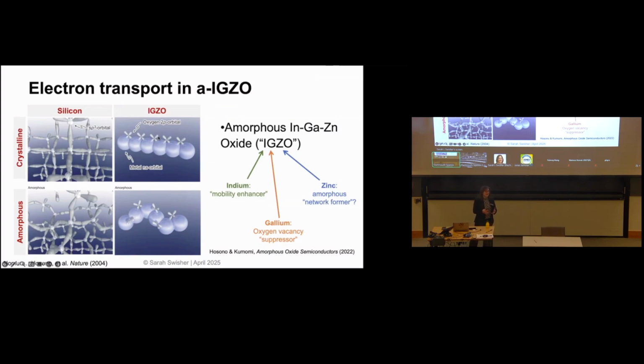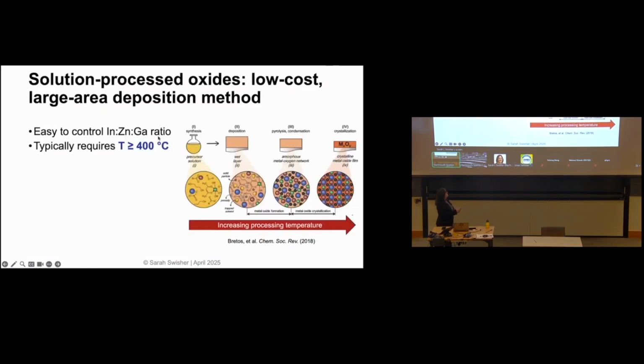A solution process is nice because instead of taking your substrate and putting it into a vacuum and trying to deposit a thin film that way, we literally just take salt and dissolve it into a solvent, and we spin a layer onto the substrate. And when you heat that up, it turns into a semiconductor. So this is what we would call our precursor solution. And you break down these precursors by adding heat. Eventually, the metal ions will grab onto some of those oxygens to form the oxide. And if you get it hot enough, eventually you get this long-range order.